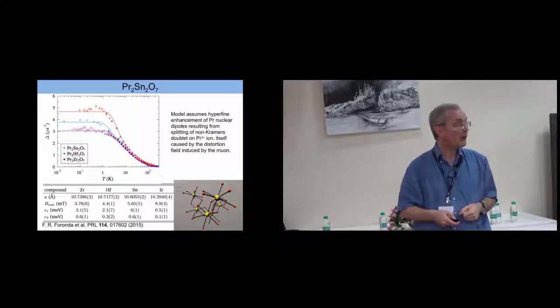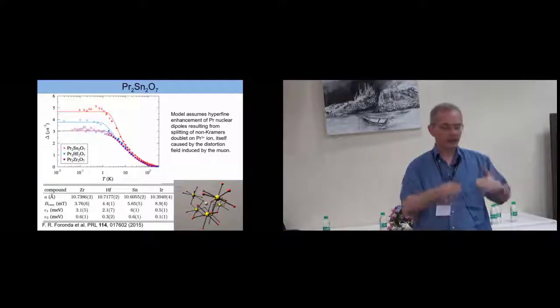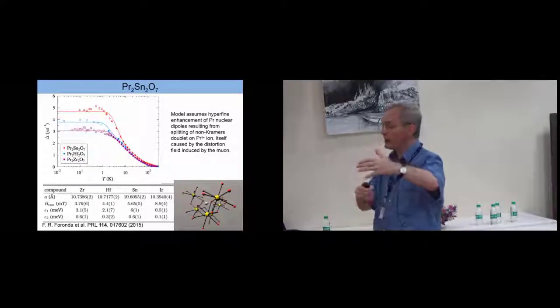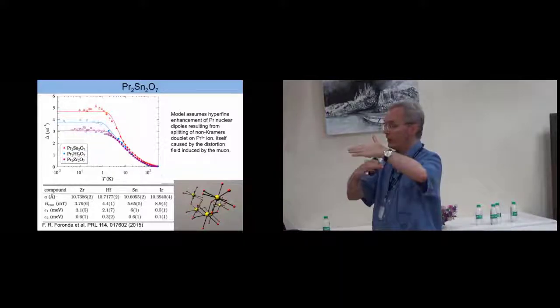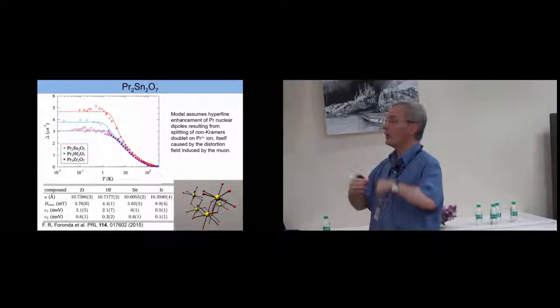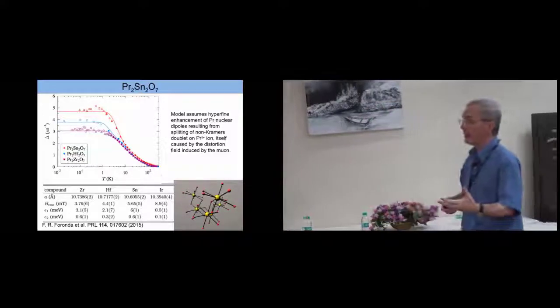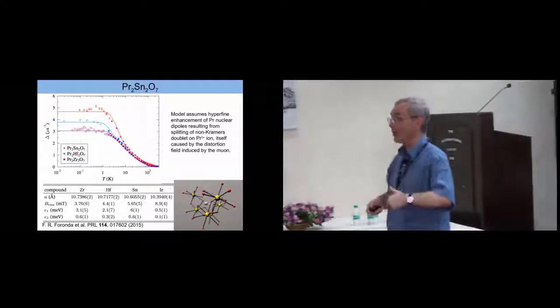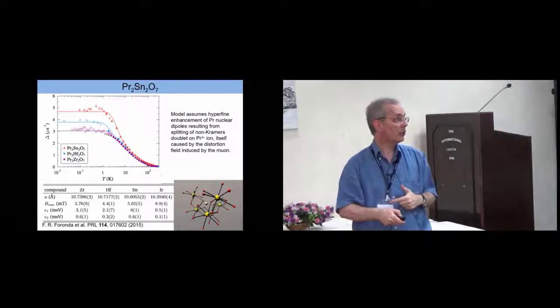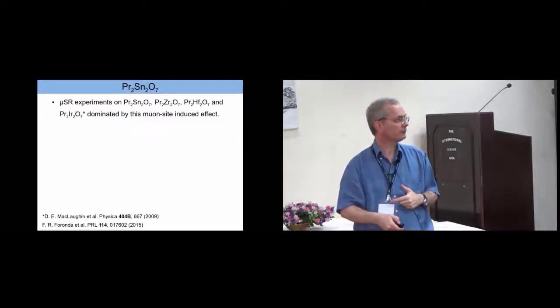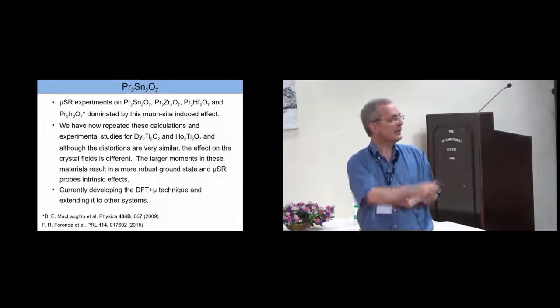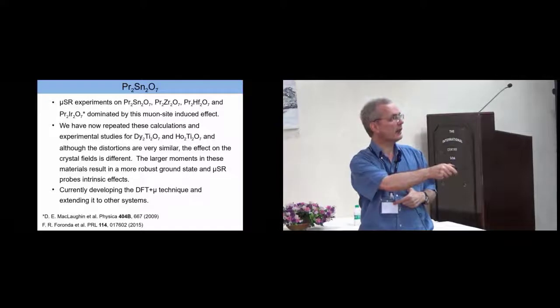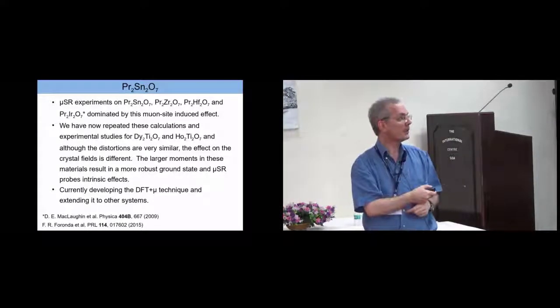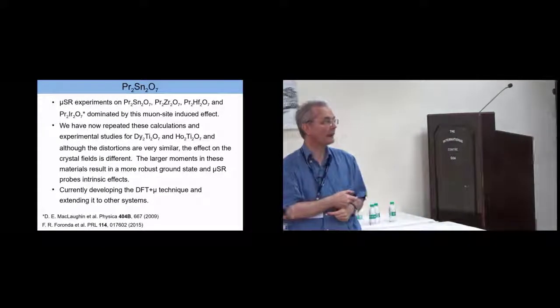So the net result of this is what we think is happening. The muon is going in, causing this distortion, changing crystal fields. The crystal field is producing then a singlet ground state. You then get hyperfine enhancement of the praseodymium moments, and that dominates the observed behavior. So these experiments on these compounds are completely dominated by this muon site-induced effect.